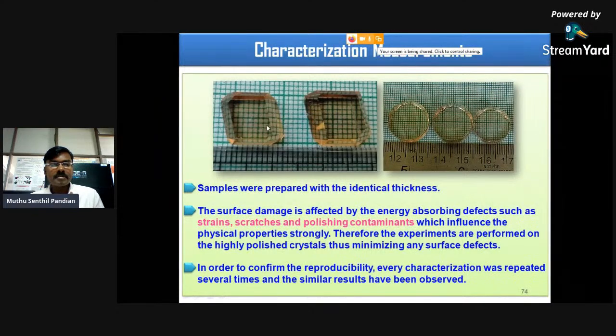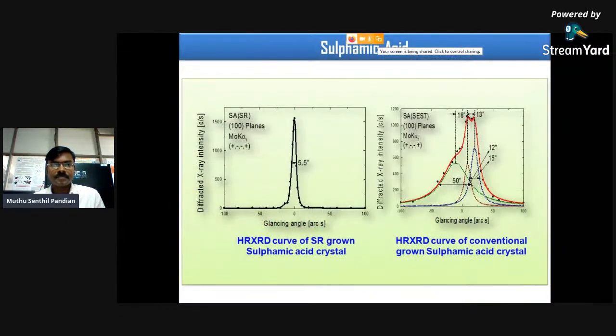So the samples, which means the crystals grown by conventional and SR method, were prepared with identical thickness under identical condition. The surface damage is affected by the energy absorbing defects such as strains, scratches, and the polishing contaminants, which strongly influence the physical properties. Therefore, all the characterization experiments are performed on the highly polished crystals, thus minimizing any surface defects. In order to confirm the reproducibility of all the characterization, all the characterization techniques were repeated several times, and more or less similar results have been observed in all the characterization techniques.